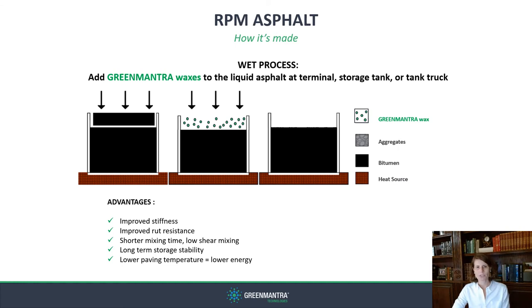One effective approach to overcome these stability challenges is to chemically modify recycled plastics to improve their compatibility with the liquid asphalt binder. Green Mantra has developed a revolutionary new RPM technology by chemically modifying recycled plastics to create specialty waxes that are designed for asphalt. These waxes increase the thermal stability of asphalt, enhancing its stiffness and rut resistance. They also allow for lower paving temperatures, which can help reduce the amount of fumes and the overall carbon footprint of a paving operation.